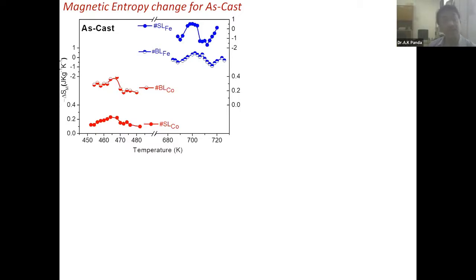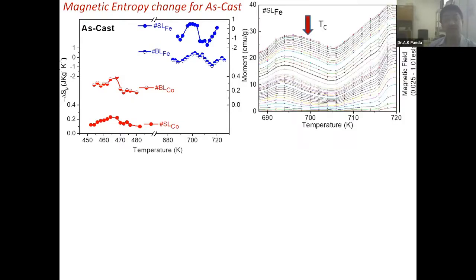SLFE and BLFE is the temperature of transformation of the iron based alloy, and BLCO and SLCO is for the temperature transformation of the cobalt based alloy. So the iron based alloy is higher. So in the same ribbon, you can find two transformation temperatures and you characterize for two different entropies. So this is the advantage of this one.